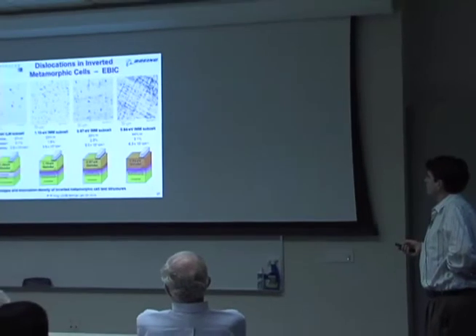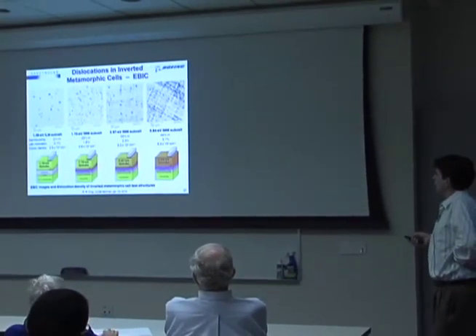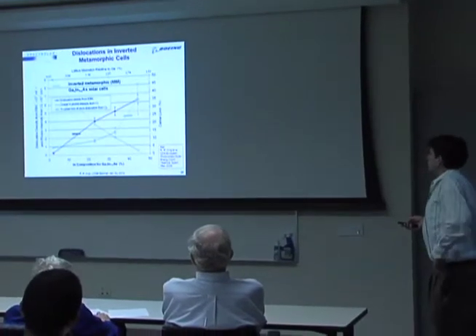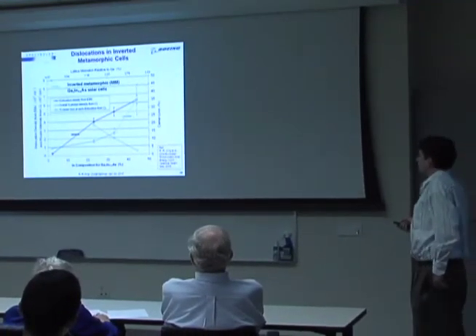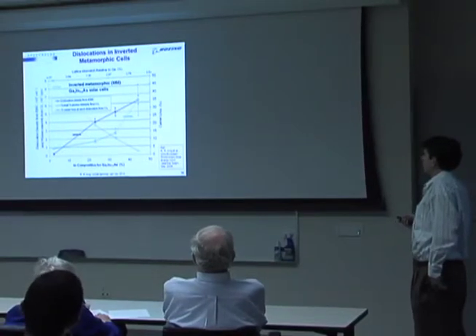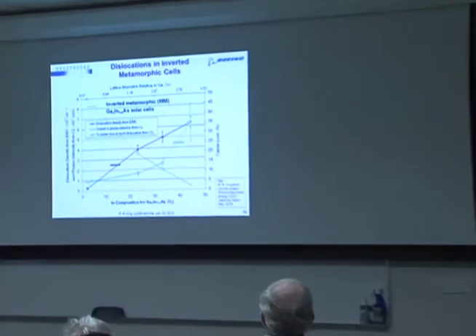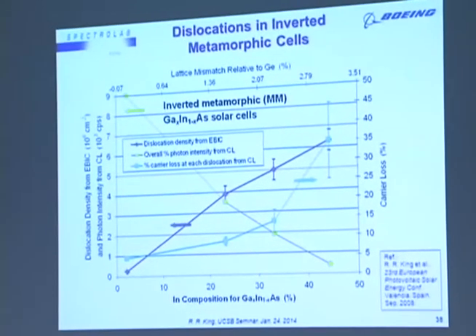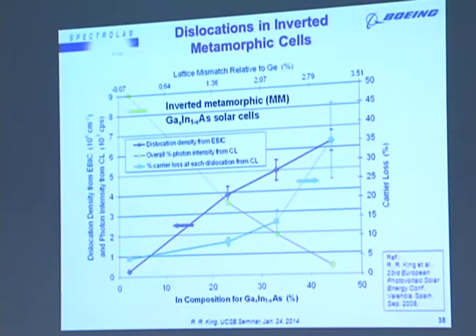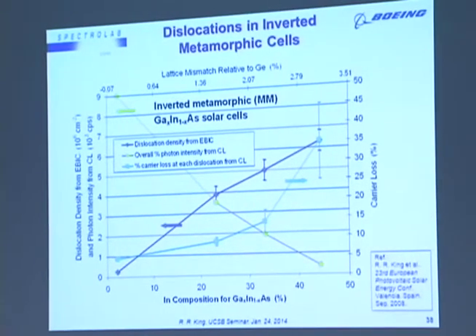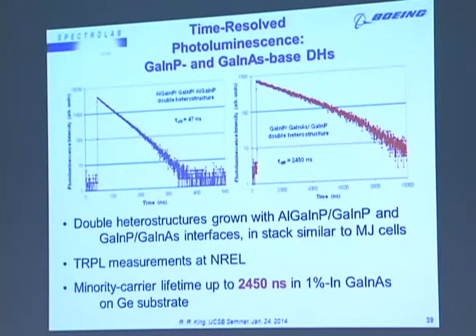We've also done studies where we vary the composition, vary the amount of lattice mismatch. As you can see, with more lattice mismatch, we are encountering more defects. But very significantly, not only does the dislocation density go up, which is shown in blue as we increase the indium composition, but the effectiveness at each dislocation at mediating recombination also increases. So this is the percent carrier loss at each dislocation. So you can see that each dislocation is, in addition to being more abundant, they're also more effective at causing recombination, unfortunately for us.